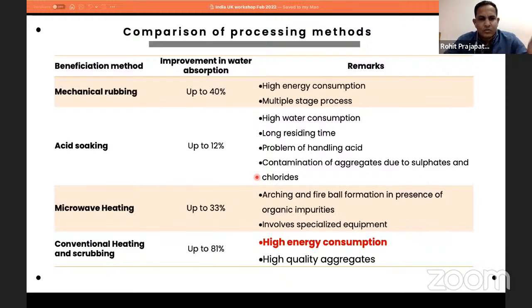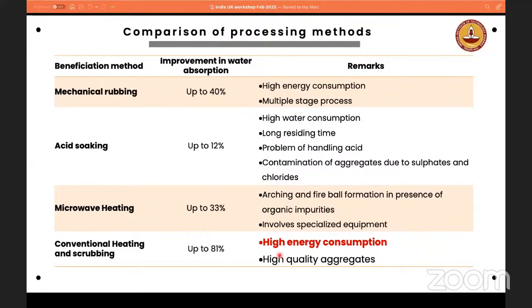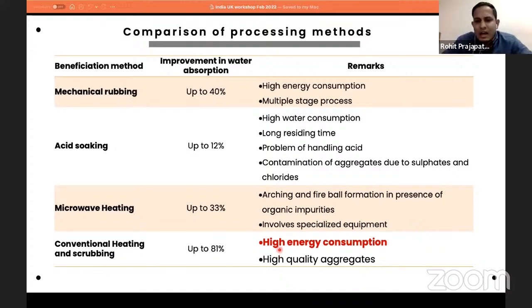So let's go back to the methods of removal of adhered mortar. So I've compared these 4 methods. So you can see that conventional heating or scrubbing, the thermomechanical treatment yields best improvement in water absorption and best efficiency in removal of adhered mortar. So you can get the high quality aggregates, the best quality aggregates, but the energy consumption is high. You can see that we have to heat the concrete to 500 degrees C.